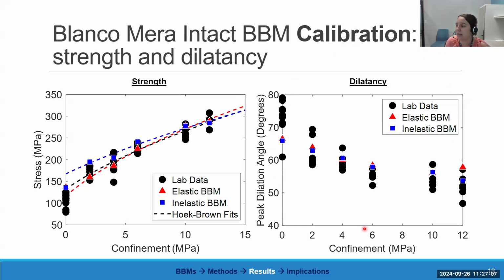On the right-hand side is a very similar plot, but for dilatancy. So we've got peak dilation in degrees plotted on the y-axis. And again, the model was calibrated to fall within approximately the middle of the range of the laboratory data. And this is true for both the elastic and inelastic block BBMs.